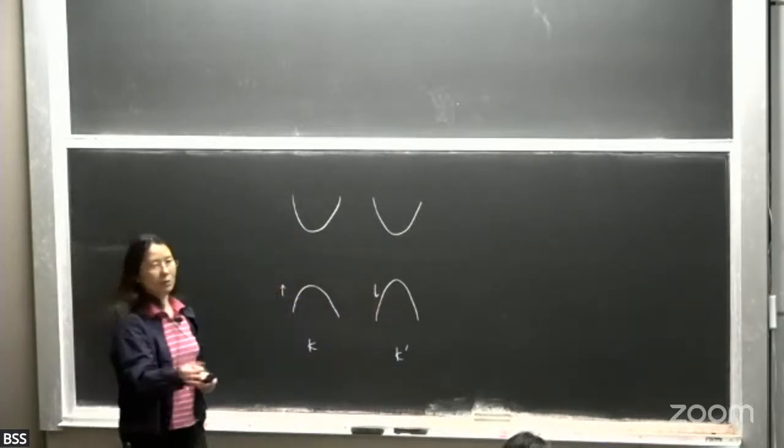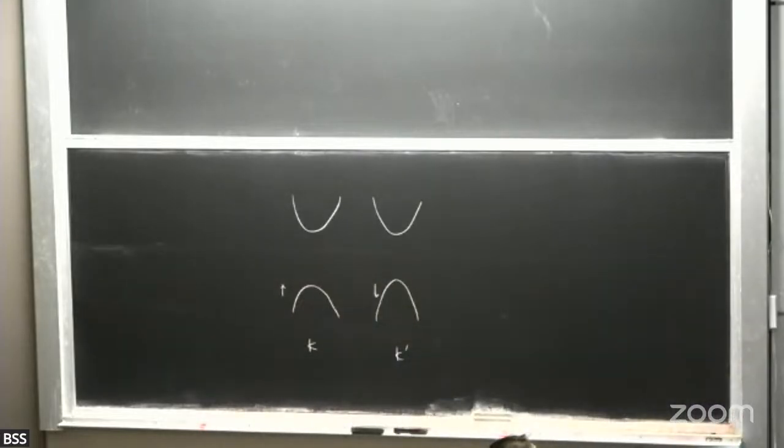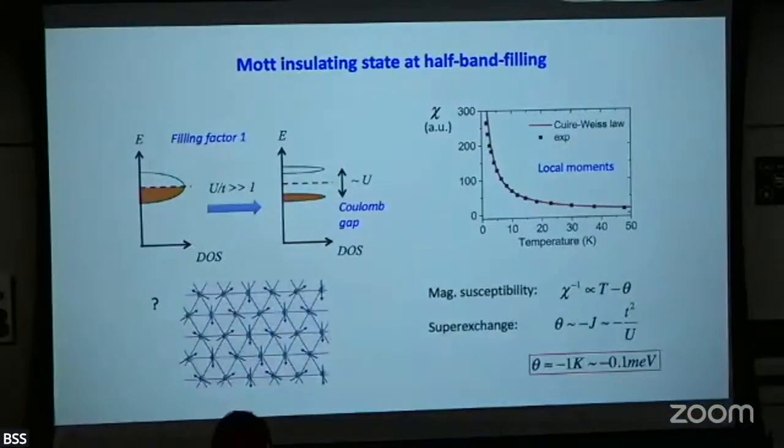This is a difficult measurement because at filling equal to 1, the spins are 8 nanometers away from each other. So in an entire sample of micron-square size, we have on the order of 10,000 spins. How do you measure the susceptibility of 10,000 spins which are embedded in many other spins? You have boron nitride, you have graphene, this and that.